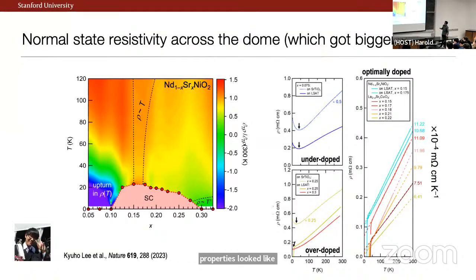There's a lot of detail here, but let me just say that firstly, at the peak of the superconducting dome, we found a very narrow region where the resistivity varies linearly in temperature in this kind of regime. And for the specialists out there, what was striking to us was that not just in qualitative form, but even in absolute magnitude, it was very similar to what you see in the cuprates. So these are various 214 cuprate single crystals, and you can see that the slope is almost the same.